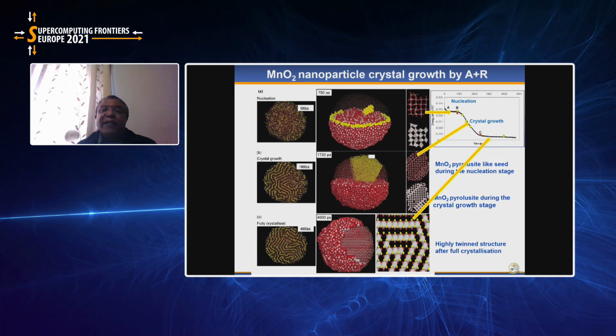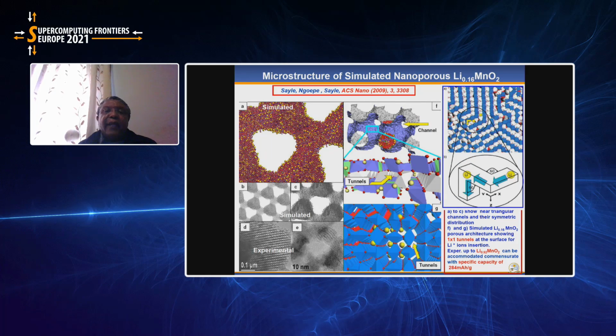which we called amorphization recrystallization method, which is a technique that is able to amorphize the material and leave it to evolve. And as it evolves, we can see a stage where the configuration energy stays constant, which is a process of nucleation, and where it drops, which is associated with crystal growth, and where it levels again, associated with the fully crystallized materials. Now, these techniques are able to give us, for example, in this case, a nanoporous structure